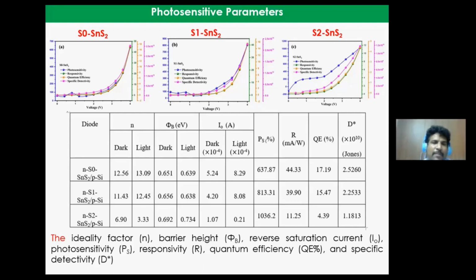My prediction is that if the flat sheets are combined together, they can form easy transportation of electrons; if you form this disc shape, there is a discontinuity from one layer to another layer. Because the layer is synthesized and then formed as a thin film, the seating of flat layers is easy, so tin disulfide flat layers show an ideality factor closer to an ideal diode. We have also compared the photosensitivity.